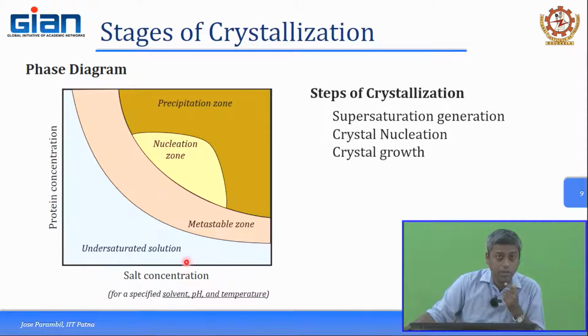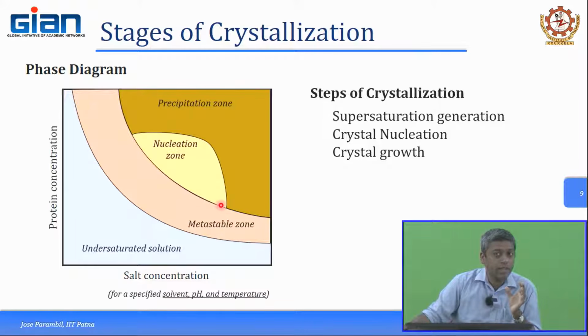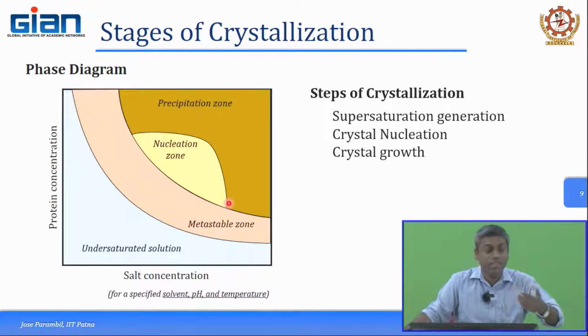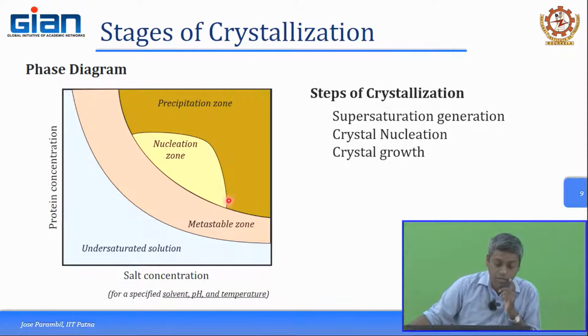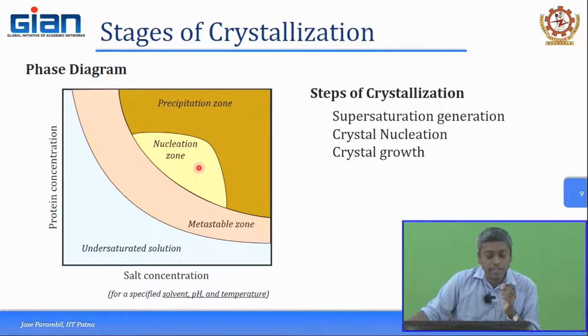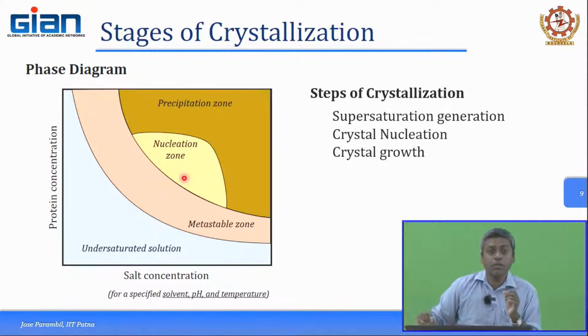This is supersaturated, but as I told you, within this metastable zone, this is a region where it can be in equilibrium, but typically nucleation is absent in this, because there is not enough protein driving force or excess protein in order to drive the nucleation process. What happens is, in the nucleation zone, if you are able to regulate your concentration within the nucleation zone, typically speaking, you might see spontaneous nucleation.